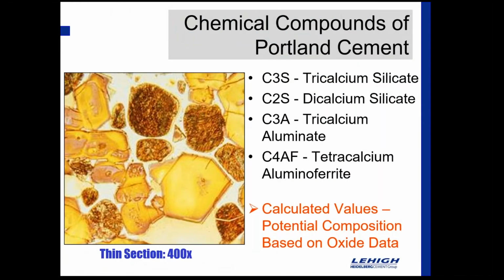And so once we have those oxides calculated, then we can start to do some calculated value work and put together the potential composition of the cement using the Bogue equations, based on the oxide data we generated. And so that's where we're going to start to hang numbers on things like C3S, tricalcium silicate, C2S, dicalcium silicate, C3A, tricalcium aluminate, and C4AF, tetracalcium aluminoferrite. And so that sounds okay, but what does that really mean?